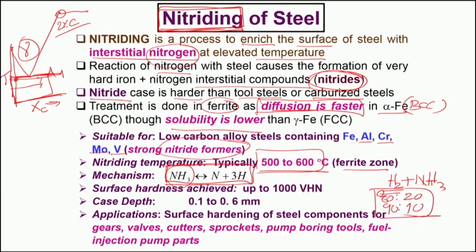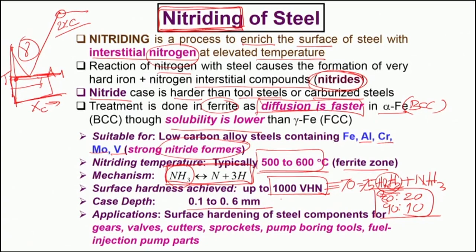More hydrogen is used because hydrogen creates conditions whereby surface oxides get reduced easily and nitrogen can move in. There is also a school of thought that hydrogen helps create a thin plasma which removes scale and oxides. This process can achieve extremely high hardness — typically in the range of 950–1000 Vickers hardness number and easily 70 or even 75 HRC. The depth could be 0.1 to 0.6 millimeters, close to a millimeter, and applications cover a very wide range of steel components.